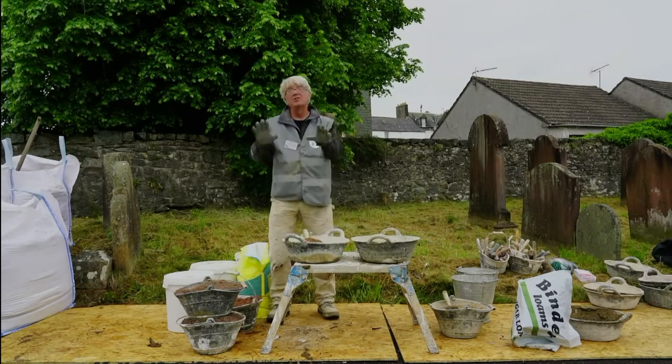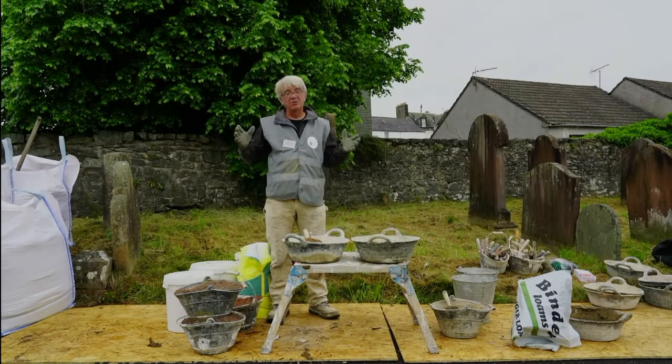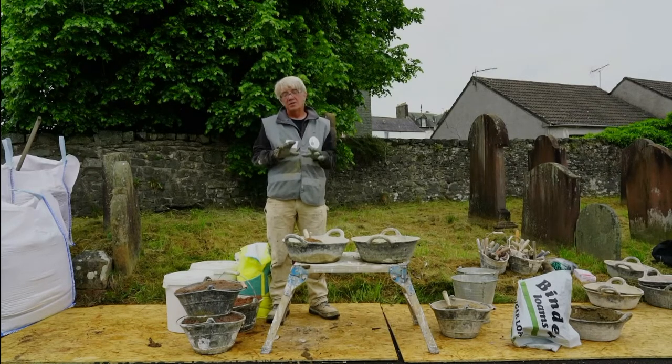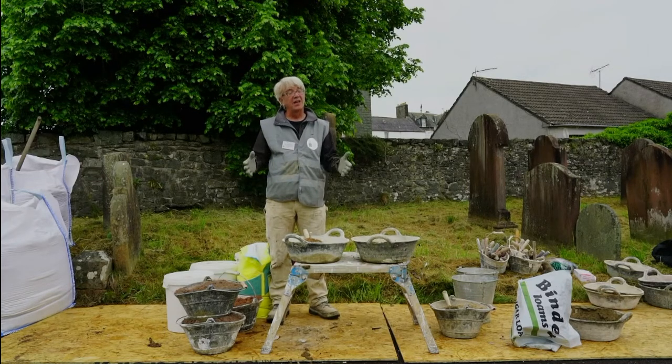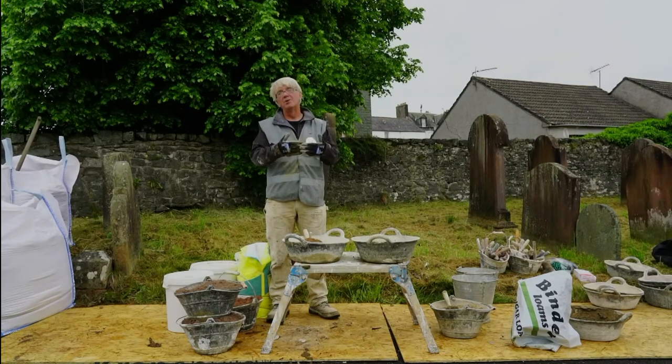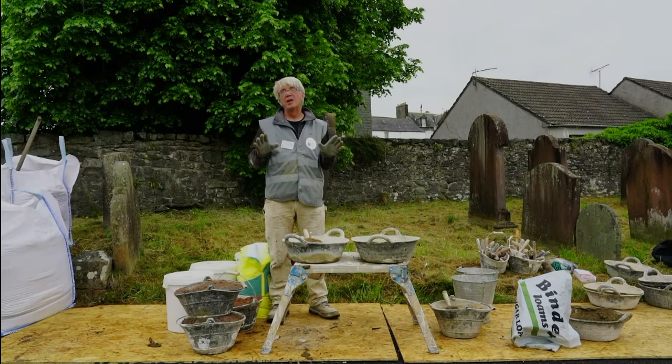Yeah. And again, scientists will deny this, except some. If you ever read any chemist about this, Robert Boynton, who was an American chemist, he's adamant, and he's also adamant that it's good to have some clay, which is why I like that. The fact that traditional dug sands had some clay in them is a good thing, not a bad thing, because you'll get a very feeble hydraulic reaction between the clay and the lime. So an earth lime mortar sets by drying and reaction, and doesn't need to carbonate. It's not that it won't carbonate, but it doesn't need to carbonate to set, whereas the mortars we're about to mix need to carbonate to set. So there's a different thing going on in there, because it does defy what I'm about to say to you about temperature of slake and so on.